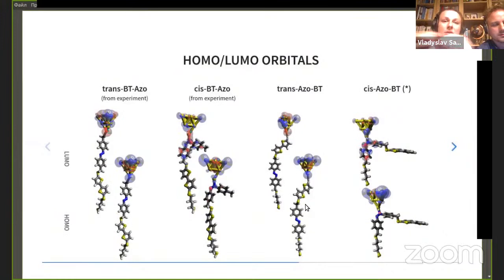What is important is that from experiment, it was shown that depending on the trans and cis isomerization state of the molecule, we basically have off state, which is trans, and on state, which is cis. And we try to explain why it happens for trans and cis isomerization. And here you see partially the answer. The delocalization of the electron on LUMO and HOMO orbitals is located exclusively on gold tips for trans isomers and includes part of the organic molecule in case of cis. This is, let's say, the proof why cis state is on and trans state is off. Trans state is acting as an insulator.